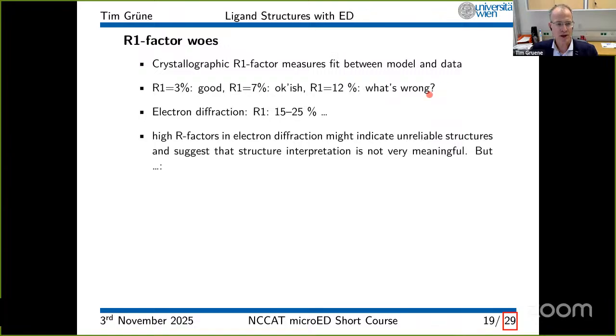When you turn to electron diffraction data and you only use kinematical refinement programs and don't take care of the specifics of electron diffraction, you still get nice structures like I showed you before, but the R value is really, really high. But you have to bear in mind that you cannot compare pears and apples. R values from electron diffraction have a very different meaning from R values from X-ray diffraction, and you still get a lot of information from the structure despite very high R values.